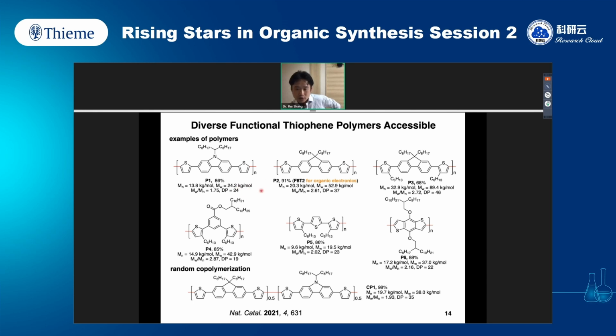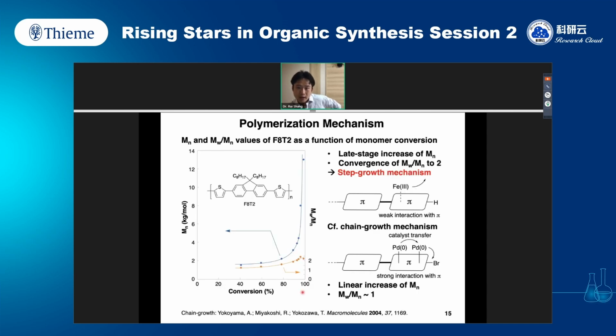On this slide, I show you several representative scope examples for the iron-catalyzed CH activation reaction. It tolerates several functional groups, and we can use it to make regiospecifically alkylated polythiophenes. We can also make copolymers by applying different monomers together. We just put the monomers into the reaction, so we get copolymers, but it's a random copolymer. It's not a sequentially controlled polymer. Regarding the polymerization mechanism, the iron-catalyzed polycondensation proceeds through a step-growth mechanism, because of the very weak interaction of iron-3 with the pi system. This is our hypothesis, actually.